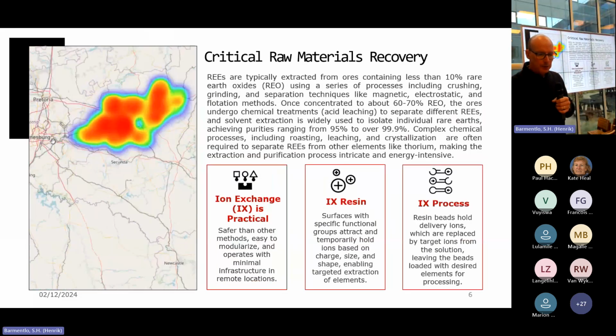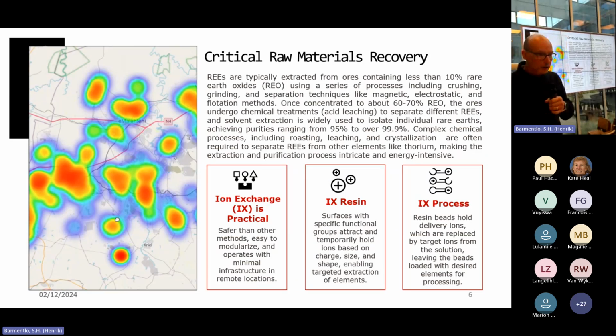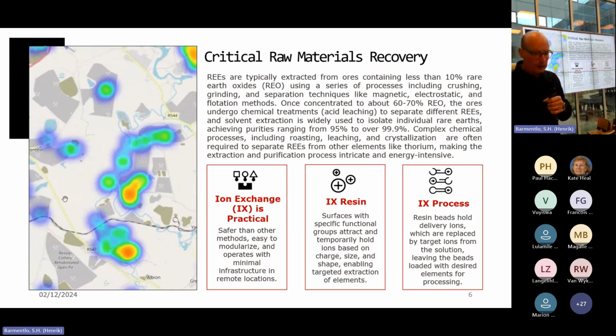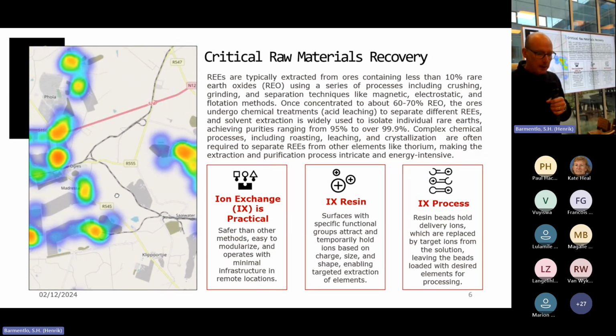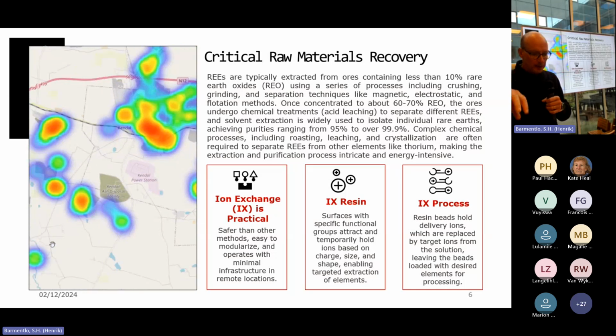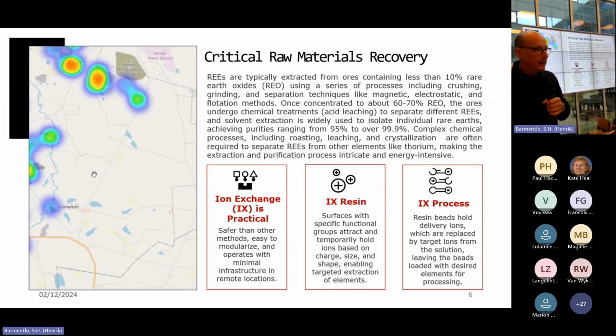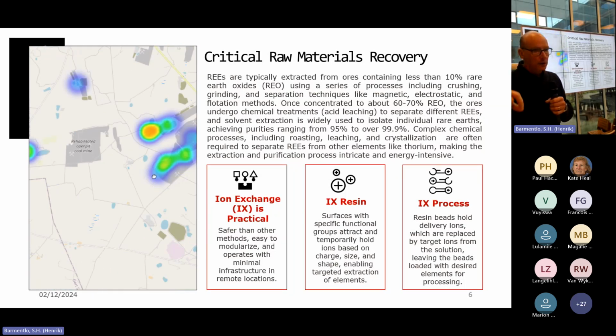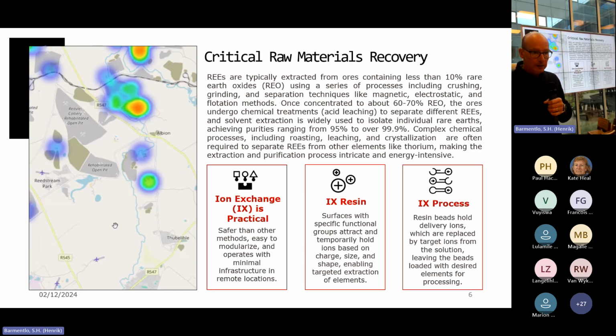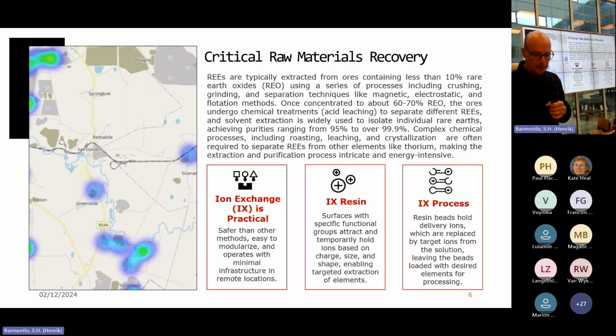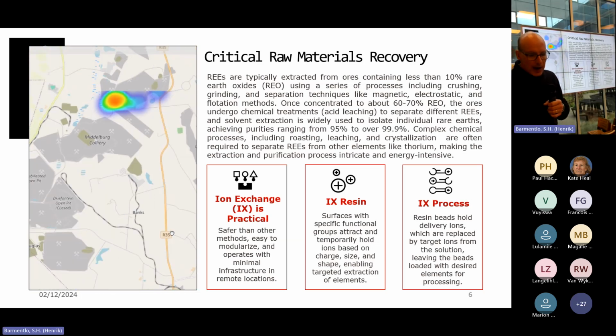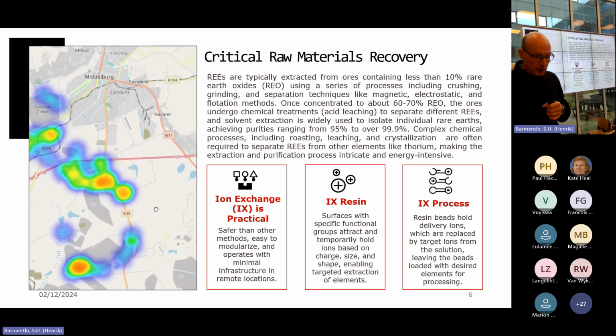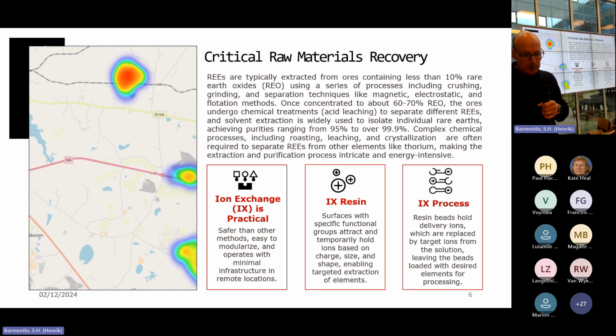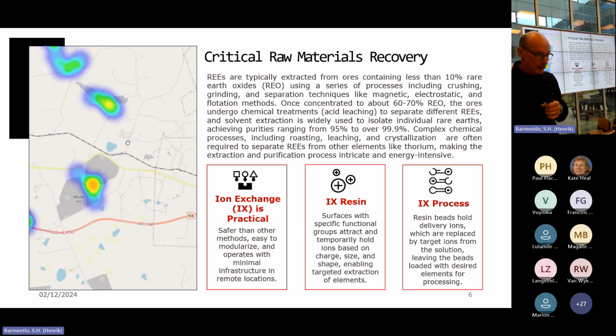So what we see is how the concentration of AMD varies across these different mine sites. In that map, you'll see that those little gray areas are typically these tailings dams. They're crushed rock to minus 75 microns, or they're fly ash. Ion exchange is a practical technology, and typically we would want to use a resin.